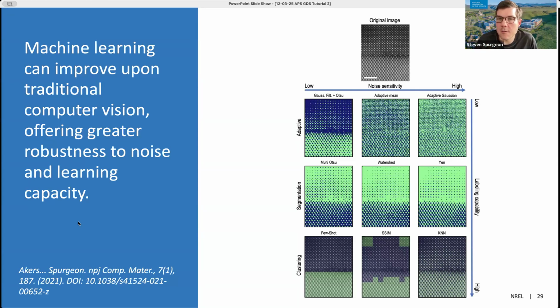So there's a variety of approaches, again, like Gaussian filtering, Otsu's method, adaptive mean thresholding, Gaussian-based thresholding, that are very lightweight and don't require a ton of upfront work necessarily, but they have very little learning capacity, labeling capacity, versus clustering approaches, structural similarity, indexing approaches, even few-shot machine learning approaches require more upfront effort to develop, but they can have a better capacity to describe materials microstructures and better transferability to new scenarios where we have different noise signatures or different artifacts within the data. So the advantage of machine learning is that we can move from these very time-consuming, fine-tuned models that are very brittle to ones that are potentially more transferable.